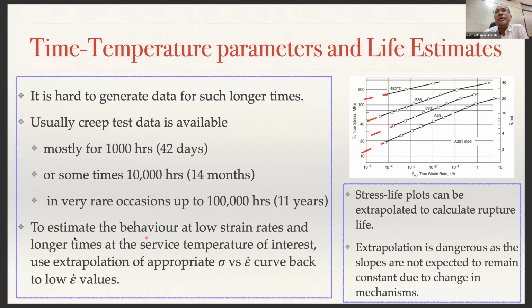So now if you have to estimate the behavior at low strain rates and a longer time for a service temperature of interest, what you would typically do is extrapolate these lines and find out the critical secondary creep strain rate, right? So this stress life plot one can obtain by extrapolating the calculated rupture life. However, please keep in mind, extrapolation is always dangerous, right?